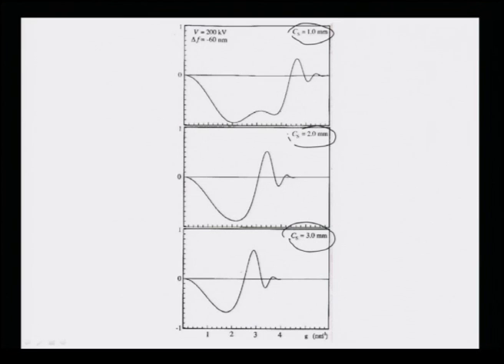For one, the transfer function has a very large width before the first zero comes here, and as the CS increases, the zero is slowly moving to the left side, to the lower value of g, and therefore a lesser number of spatial frequencies can be transferred in the actual microscope. This is done at a fixed value of defocus, minus 60 nanometers. So once we optimize the CS value, here it is seen that the optimum CS value is 1,